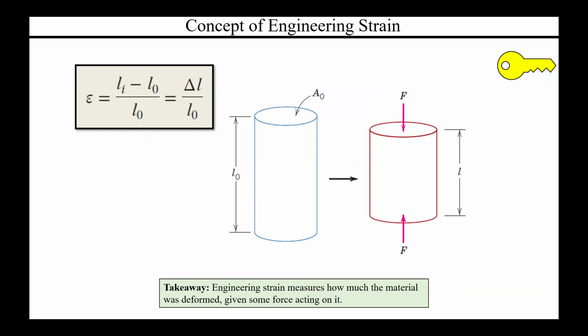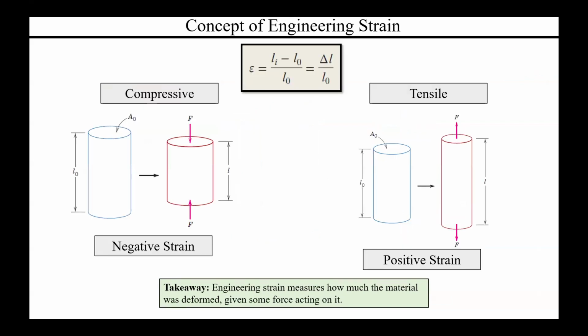And then that force will ultimately cause the material to change, and this is where the strain comes from. Strain, at least in the context of something like tensile or compressive, is fairly straightforward. You apply a force, the material changes along one direction, so you can simply measure the strain as the change along that direction: your current length versus the initial conditions. Because of that, you'll end up finding that you have a negative and positive strain variant. In the case of compressive, the negative strain implies that the material has gotten smaller, and in tensile, the positive implies that it's gotten bigger. That is purely due to convention. You could flip your L naught and Li and redefine this somehow, but the standard convention is that negative strain means it got smaller and positive strain means it got larger.